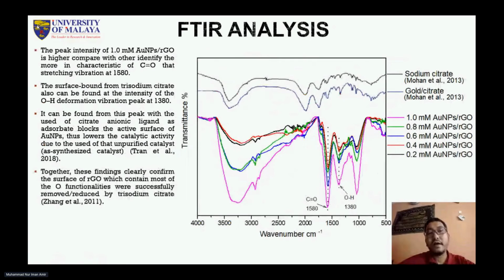While for the FTIR analysis with different concentrations of gold nanoparticles on the surface of reduced graphene oxide, we can confirm based on the carbonyl and hydroxyl functional groups that using the higher concentration interferes, due to the constant concentration of trisodium citrate during the synthesis process. So this finding clearly confirms the surface of reduced graphene oxide, which contains most of the oxygen functionalities, was successfully removed or reduced by the trisodium citrate.